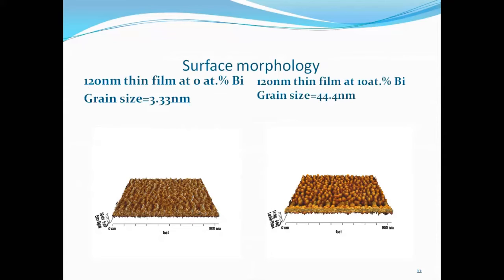You can see they are the same thickness, 120 nanometers thick, both of them, but the difference here is the bismuth concentration. The first one, which was at 0% bismuth concentration, the grain size was found to be 3.33 nanometers. And you can see the one that was at 10% atomic bismuth concentration, the grain size was 44.4 nanometers. This clearly indicates that the grain size increases with bismuth concentration.